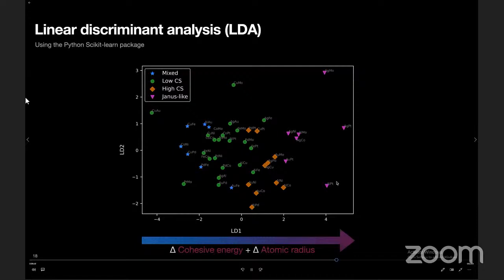The method was quite good at separating the different types of structures, and if we look at this first axis and read what features are predominantly constituting this axis, we find that they are the cohesive energy difference and atomic radii difference. So essentially, the LDA analysis results show that the deciding factors of the final structures we see in the MD results are the cohesive energy and atomic radii difference.